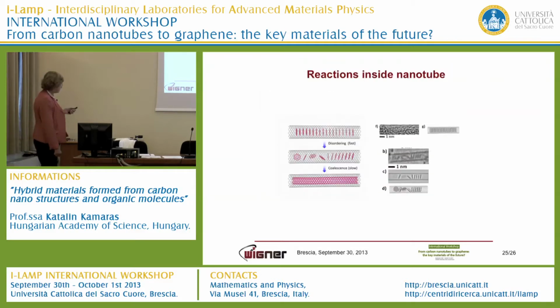Okay, so this is now the picture of it, and you can actually follow this just by following your microscopy images with time, because if you now increase the kinetic energy just by irradiation with electrons, then that's a very analogous process. And what you can see is that these are the first steps of the polymerization. You just get a little more disorder here, and then you get a slow coalescence, and there might be some kinds of steps in between.